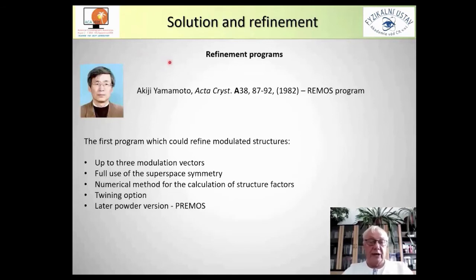The first program for refining modulated structures was written by Akiji Yamamoto in 1982. This program was able to use up to 3 modulation vectors. It used the full advantage of superspace symmetry and a numerical method for calculation of the structure factor. This numerical method was based on Gaussian integration. It had a very nice twinning option, and later a program was also developed for refining modulated structures from powder diffraction data.